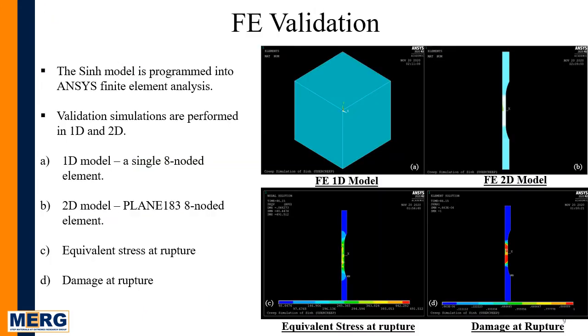The finite element validation simulations are conducted for both the 1D and 2D models. To do so, the sinh model rate-based equations are programmed into the ANSYS finite element through updating a user creep subroutine. The validation simulations are conducted up to the rupture time. For the 1D model, a single 8-noded element, and for the 2D model, PLANE183 8-noded elements are chosen. The equivalent stress and damage at rupture for the 2D model are shown in these two figures.